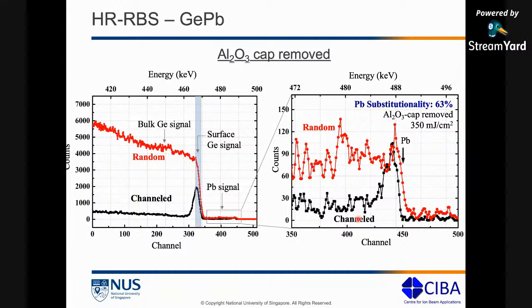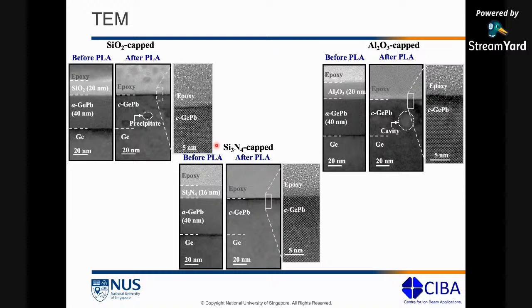So this is again with whatever lead is left behind. Now, most of the lead has been lost in the capping layers. This is only with the lead that is left behind. And then, just like I told you before, we corroborated this data with the complementary technique. We did a cross-sectional TEM imaging on all of these samples, and this kind of corroborated our analysis from RBS.